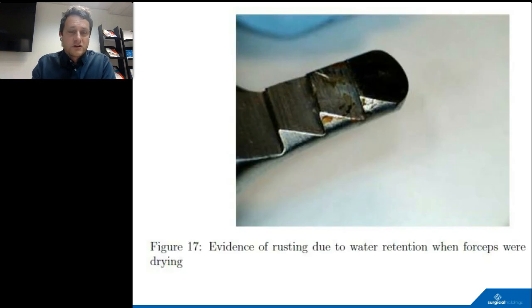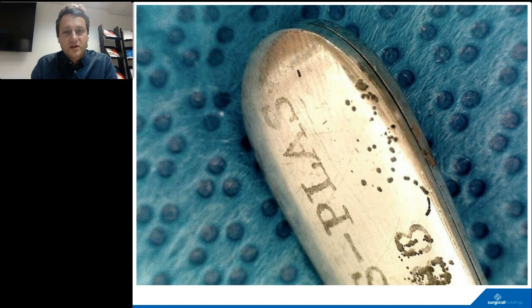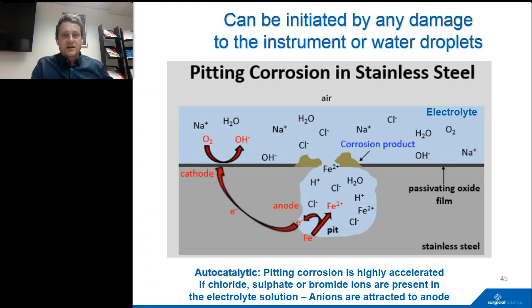And just to show you what water on a ratchet on a forceps does, if the water is left on the forceps, it can damage that passive layer, leading to staining, like an image such as this. And you also might have heard of pitting. Well, here's the end of a forceps showing some real quite aggressive pitting. Pitting is like a cavity in the stainless steel itself. And the reason that generally comes about is just because of the presence of chlorides. You'll generally get chloride in potable water. So I guess tap water where you're not using an RO water treatment.